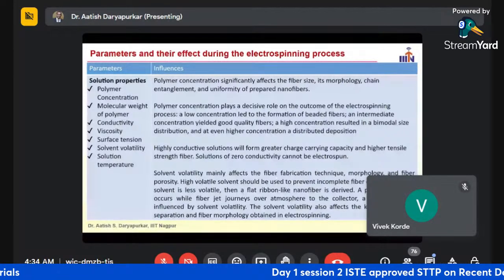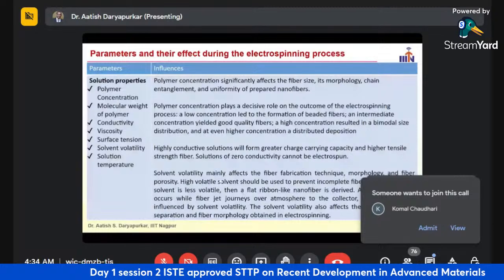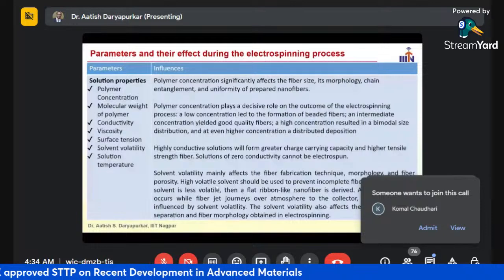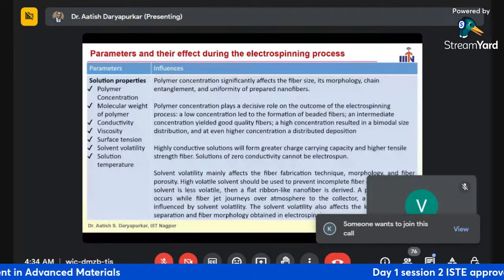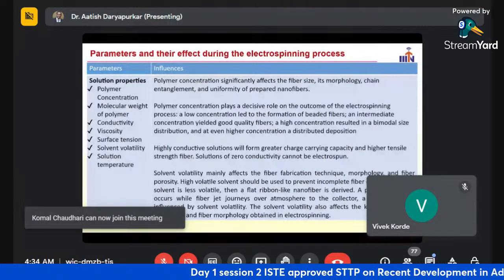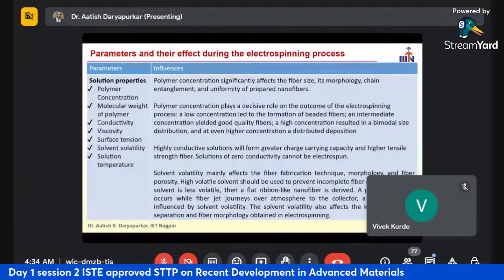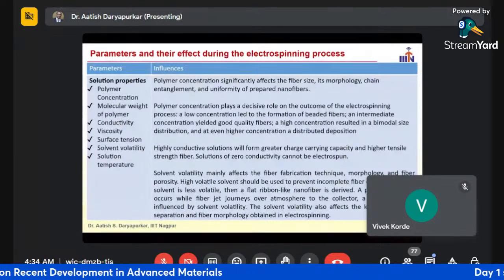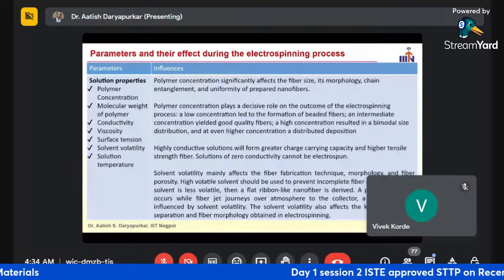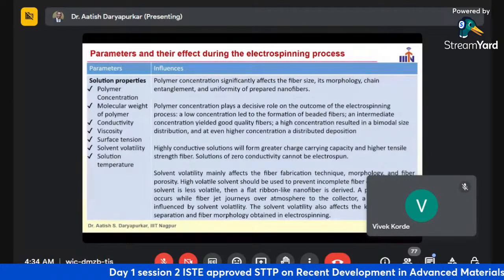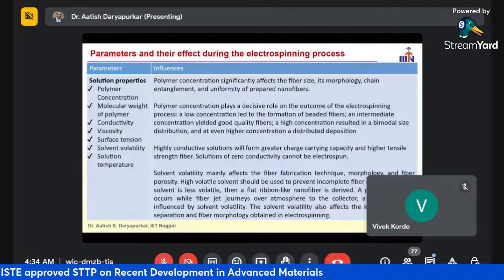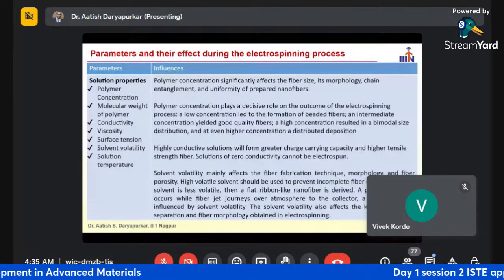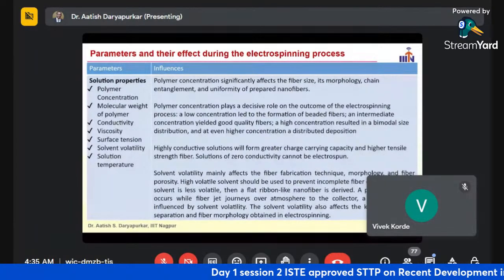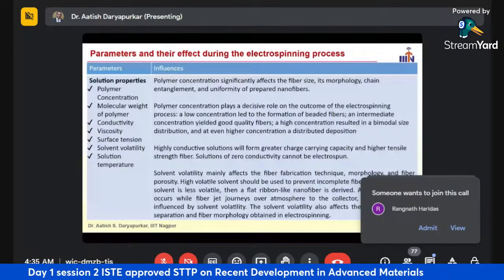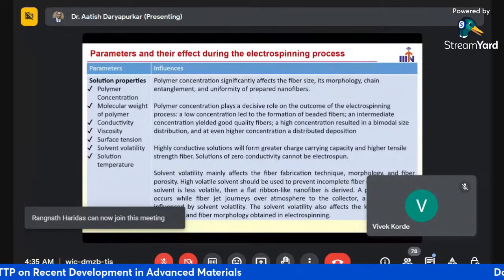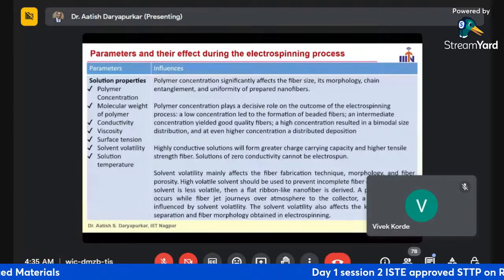Then solvent volatility mainly affects the fiber fabrication techniques, morphology, and the fiber porosity. High volatility solvent should be used. Volatile solvent should be used to prevent incomplete fiber drying. Right, when the solution gets extracted from the needle, that solution should evaporate and you can get the fibers on the collector. If the solvent is less volatile, then what will happen? Flat ribbon-like nanofiber is derived. A phase separation occurs while the fiber jet journeys through the atmosphere to the collector, a process greatly influenced by solvent volatility. The solvent volatility also affects the kinetics of phase separation and the fiber morphology obtained in electrospinning. So overall, the polymer concentration, conductivity of the solution, and volatility of the solution play a very important role to get the desired fiber.